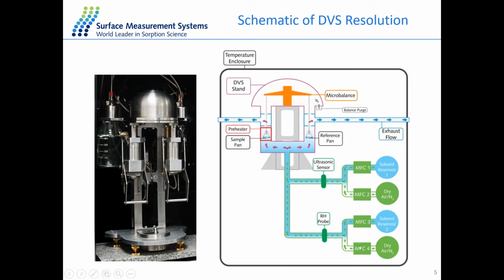So the mass flow controller inside the system will control the flow of the carrier gas and the saturated vapor in ratio to get a certain level of relative humidity or partial pressure. And then the sensor in the lines here will detect the concentration of this mixture and see if this moisture or the concentration is reaching the target value. And then this mixture will flow to both the sample chamber and the reference chamber at a constant rate.